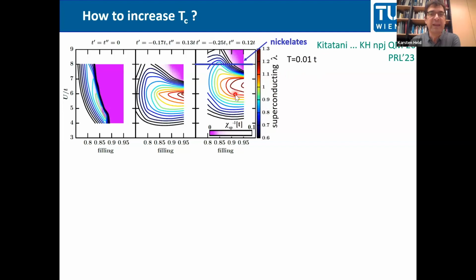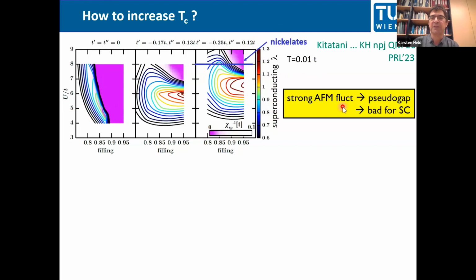And what you see here is like a fingerprint, but it's very much deformed. That is this purple thing here. So what is the purple? And it's huge for the plain Hubbard model. It's where antiferromagnetic spin fluctuations get really strong. And if they get really strong, you form a pseudogap, you lose your coherent quasi-particles, and that's bad for superconductivity. So that's why you get a superconducting dome in the first place, because you increase antiferromagnetic spin fluctuations going to half filling, but then they become too strong and TC goes down again.